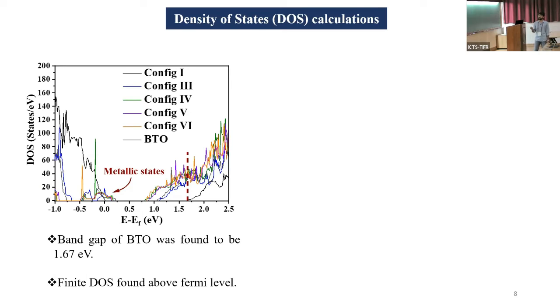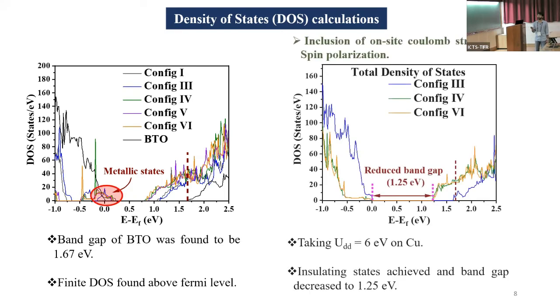This can be understood from the fact that since we have a copper 2+ ion, which is a d9 system and a Jahn-Teller active ion, the dx²-y² orbital is singly occupied and therefore spin degenerate, and therefore it leads to a conduction channel in the system, and we have finite density of states. So to lift such metallicity, we included spin polarization in our calculations.